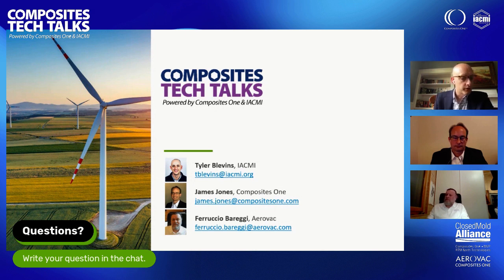Awesome, thanks, Ferruccio. So we've got another question that just popped in. What resin viscosity is typically recommended or achievable for general blade infusion? Yeah, generally you tend not to go higher than 120, 150 centipoise. It depends on the resin. Most blades are constructed from epoxy. Some are constructed from polyester. And generally, infusion polyester resins can have a lower viscosity than an epoxy. But as Ferruccio's saying, I've seen them as low as 85 centipoise up to about 300. Getting above that, it gets very difficult to flow and saturate the materials.